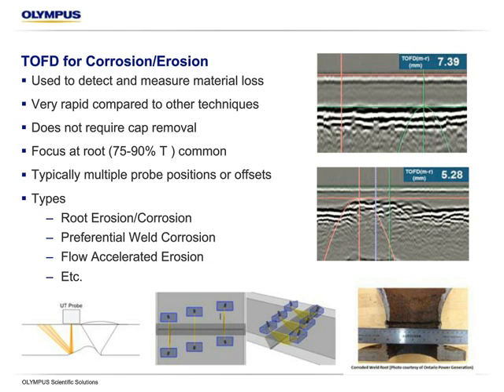We usually focus near the root, 75, 90%. Does not require cap removal, so we're able to get even areas directly under the cap because of the technique of TOFD. So it can be very good without having to remove that cap compared to, say, pulse echo conventional.